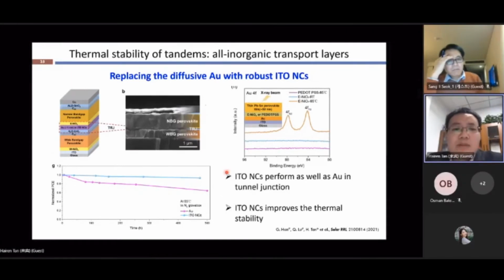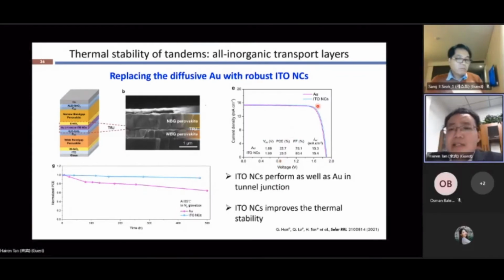To avoid the metal diffusion in the tunnel recombination junction, we replace this gold layer with a very robust ITO nanocrystalline film. We can see that using this ITO nanocrystalline layer as the tunnel recombination layer, we can still get very comparable device performance. And the good thing is that we can significantly increase the thermal stability of the tandem devices by using the ITO nanocrystalline film as the charge recombination layer.